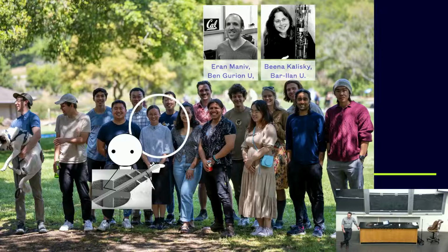Thank you, Jim, for this interesting talk. Thanks, Sean. In the niobium sulfide system, did you observe the non-volatile memory effect in the longitudinal resistivity? You measure the Hall effect, right? No, you measure all perpendicular, right? But it's not Hall effect. Hall effect implies there's a magnetic field. So it's in the transverse resistivity. So it's still even in field. It's basically the anisotropy in the conductivity tensor that you're measuring, even though it's a transverse contact. There should be a longitudinal signature as well.